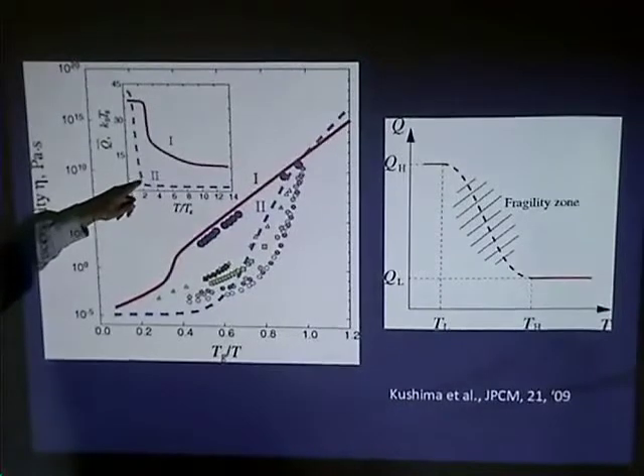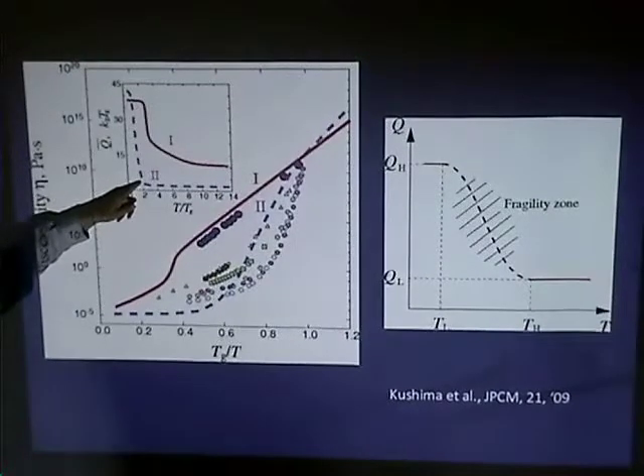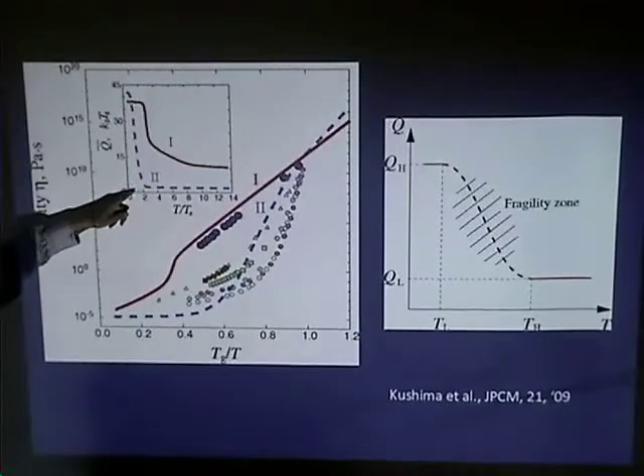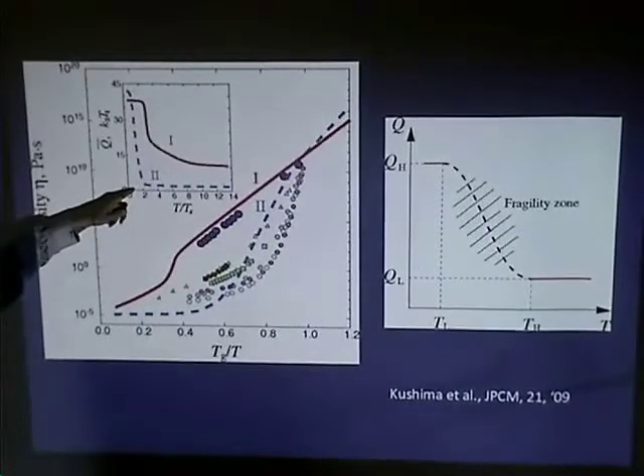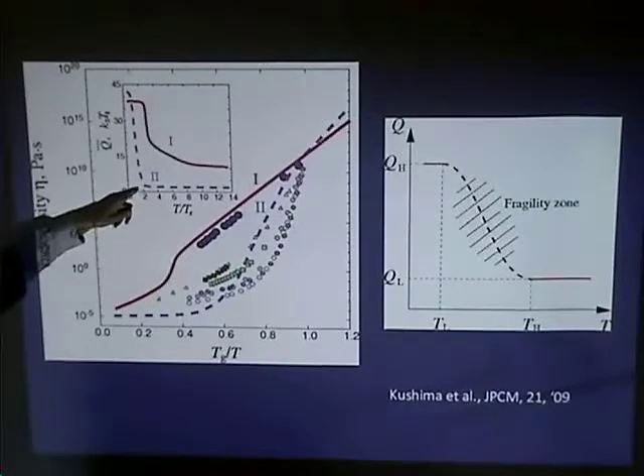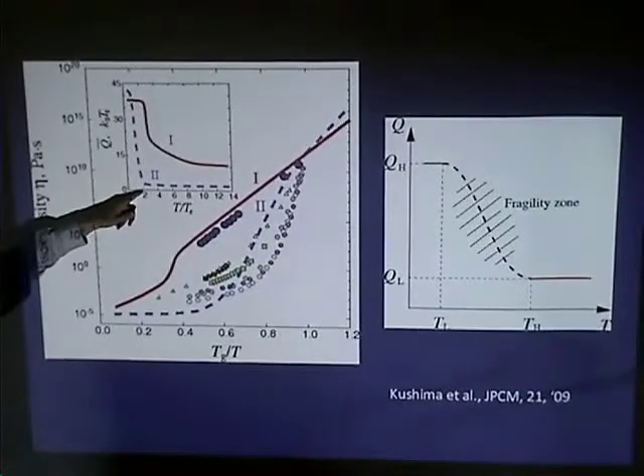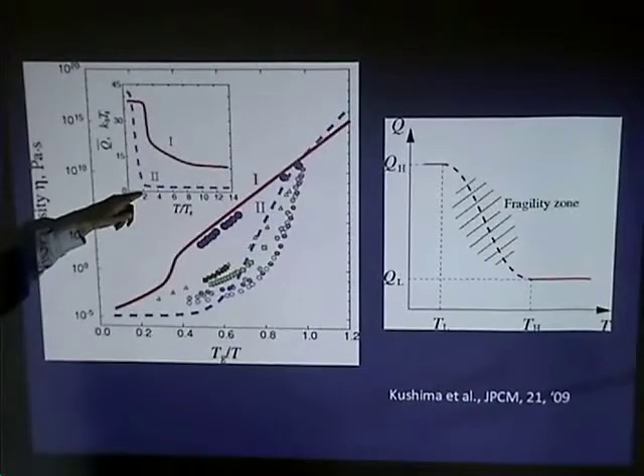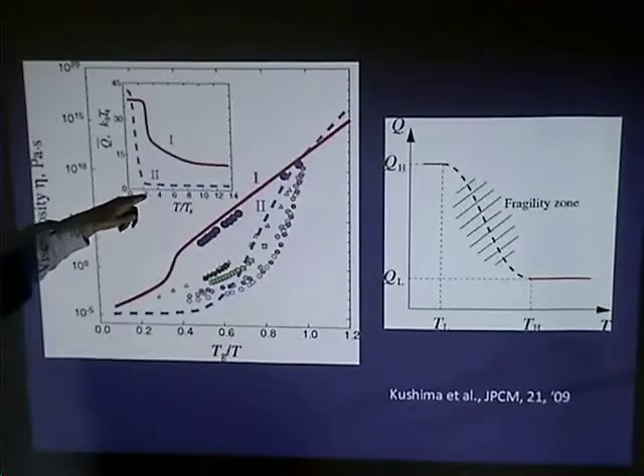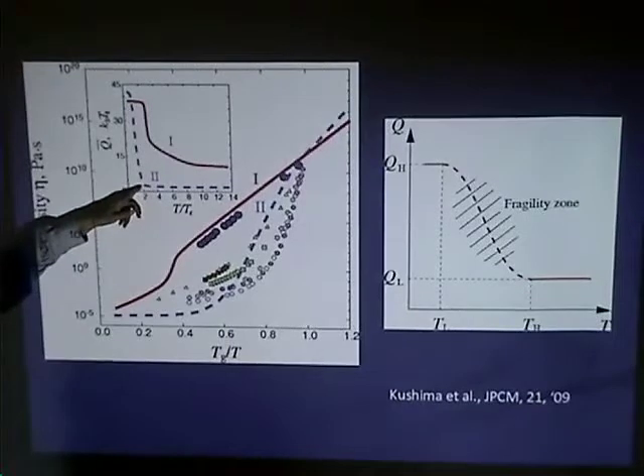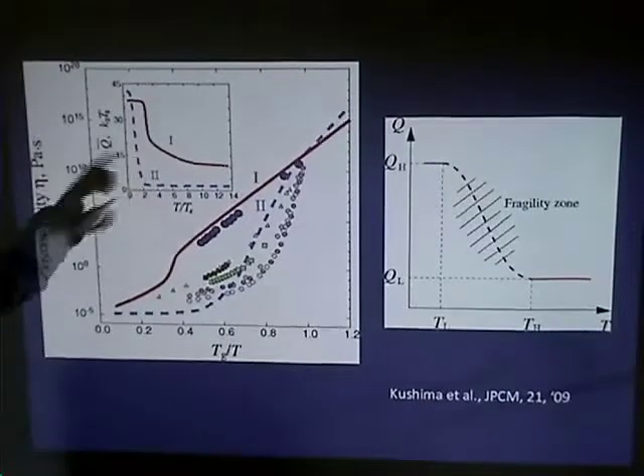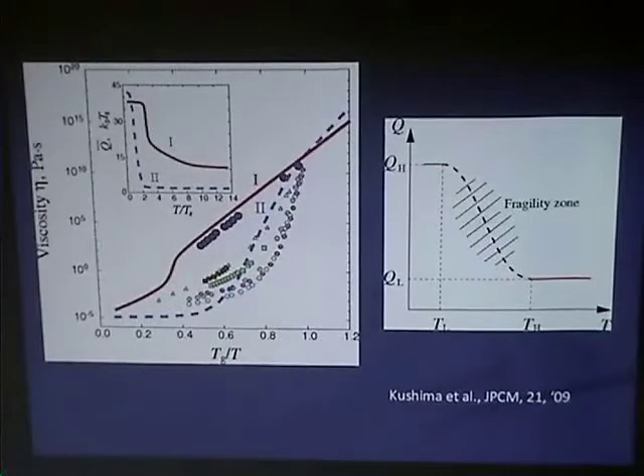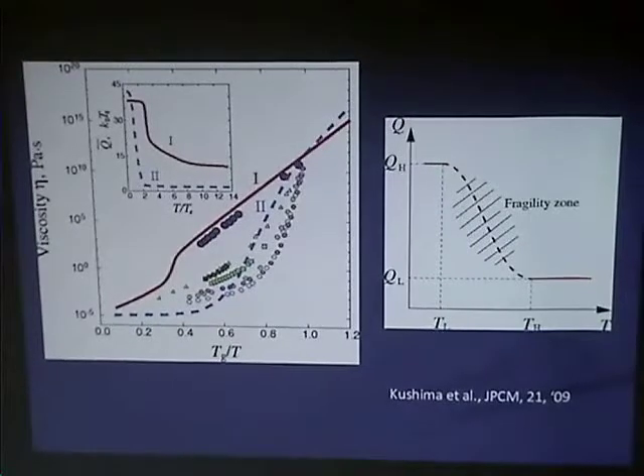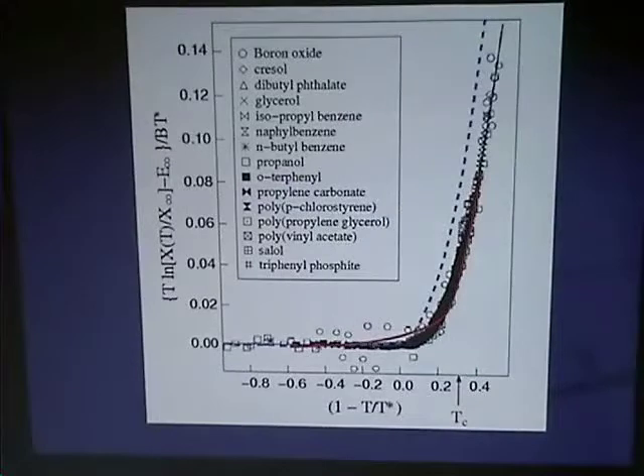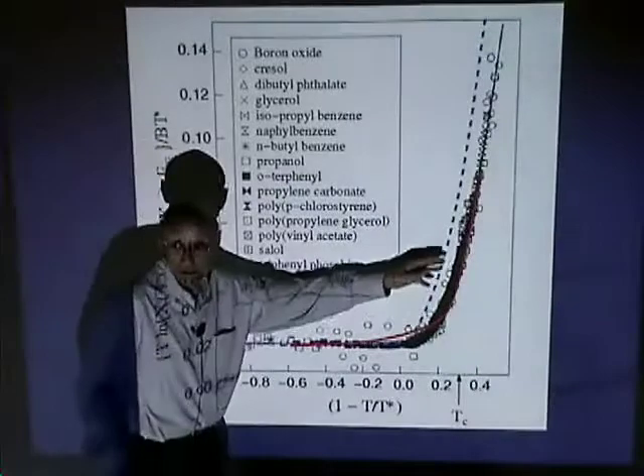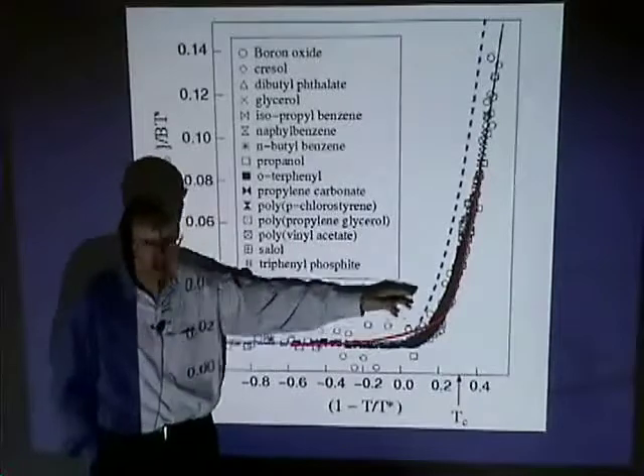It depends. What's your value of Tg for that data? Because it is a broader range for densities. Tg is pretty close to the experiment. For silica, it came almost right on. Binary linear was within 100 degrees or so. So this curve here, the one that Conrad was just talking about, is exactly the curve that we have seen previously. That rise is really sharp, and the data shows very sharp as well.